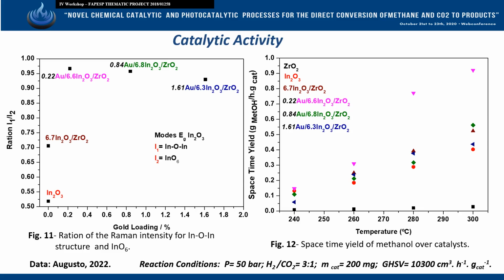In addition, with the presence of gold, the ratio of intensities for the vibrational modes follows the increasing trend up to 0.22% of gold and decreases with increases to 0.84 and 1.61% respectively. As the metallic content of gold increases, lower intensities are observed due to the presence of the nanoparticles covering some oxygen vacancies. The catalytic test at high pressure, 50 bar, for samples with 0.22, 0.84 and